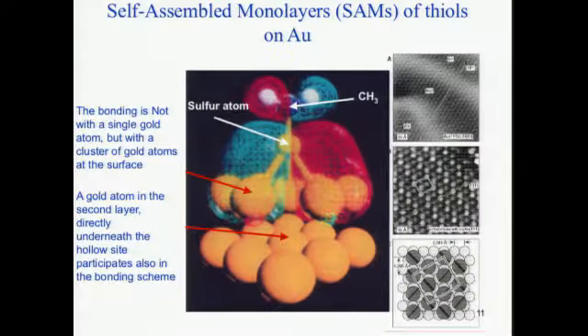So what is at the center of self-assembled monolayers is the gold-sulfur bond. That's one part. The other part is van der Waals interactions between the backbone, in the case of alkane thiols, of the alkane thiol carbon structure. And so it's well known how the sulfur bonds to the gold. You start with a gold 111, I should tell you, which is a crystallized structure of gold. And it has order, and we know the spacing between the gold atoms on the surface. And we also know what happens when you come with a sulfur atom, how it likes to grow relative to the gold surface that we're using.